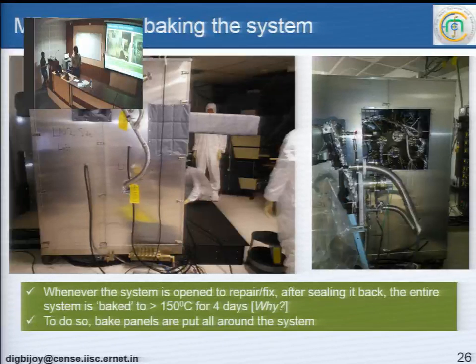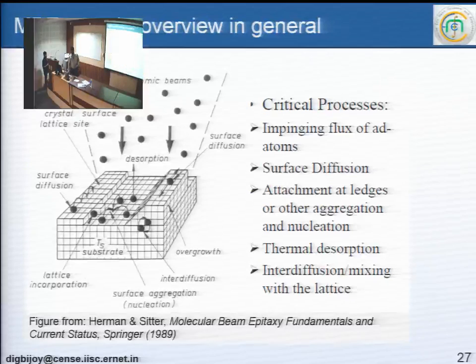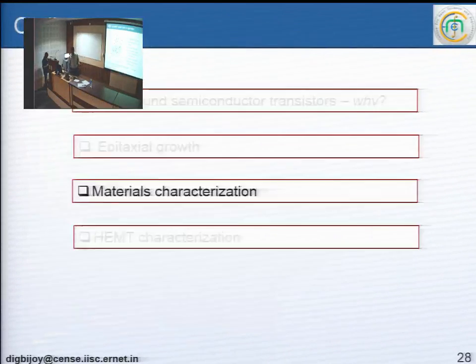Once you open the system, you have to wrap the system around with steel panels like this, and then heat up at around 150 to 200 degrees Celsius for 4 days. For 4 days, you heat the whole system up at 150 degrees Celsius. Why? Because no matter what you do, there is always one atomic layer of water vapor on any surface. To get rid of that one atomic layer of water, you have to do this, because otherwise you cannot reach 10 to the minus 11 torr. And this is how basically the growth kinetics takes place. And I'll skip this. Basically, you have all these kinds of thermodynamic processes taking place that help you to grow.